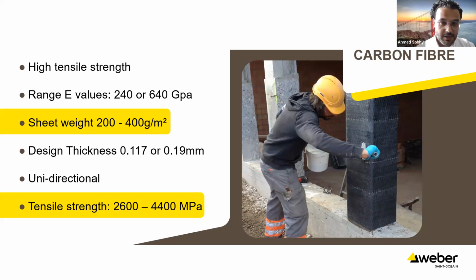One of the most important pros when we're talking about carbon fiber in general is that it's not really susceptible to creep. So in an application where sustained loading is in action, we usually specify carbon fibers. On the other hand, one of the cons of carbon fiber is that it's a conductive material. So we need to be very much aware when steel comes in contact with carbon fiber, for instance, because that will initiate a corrosion cell. So we need to apply an insulation layer.